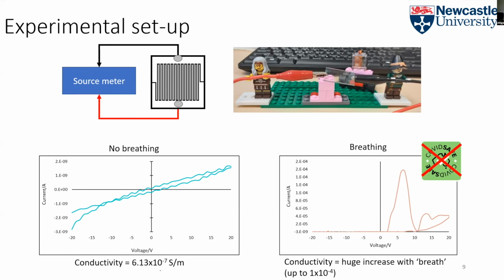But what I did realise by accidentally breathing on the sample, and you can see I've got COVID safe crossed out, defining the lab practices, but essential here, because basically I realised that when I breathed on the sample, the conductivity massively increased. So it seems like the conductivity was dependent on humidity. And this could be interesting for a lot of reasons. It could open up doors to sensing. It could open doors to using solar cells in different environments, etc., etc.